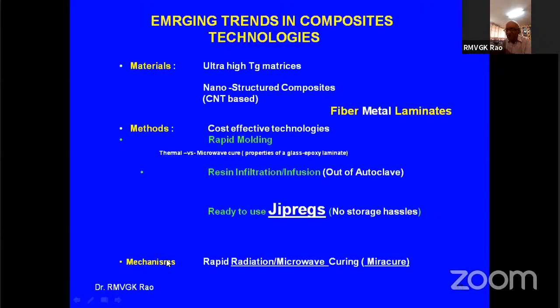The satin remains satin, the plain remains plain. Therefore, without weave distortion, you can impregnate, wet the fabric by resin film. It's called resin film transfer technique. And then you can control the fiber matrix ratio very well, 65%, 75% by volume of fiber in the matrix. Therefore, you get very high mechanical properties. It is reproducible. There is a computer controlled machine. It will dose the resin in exact quantity. There is a doctor's blade which will swipe it, make it a thin film, and it was proven in 2007.